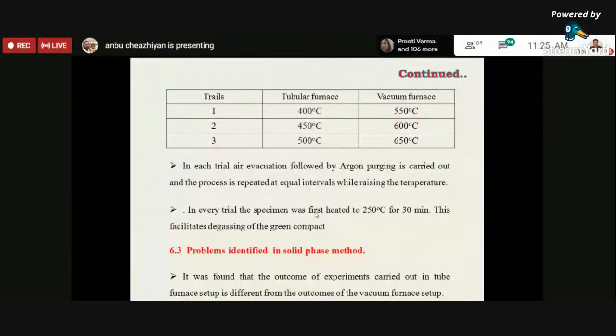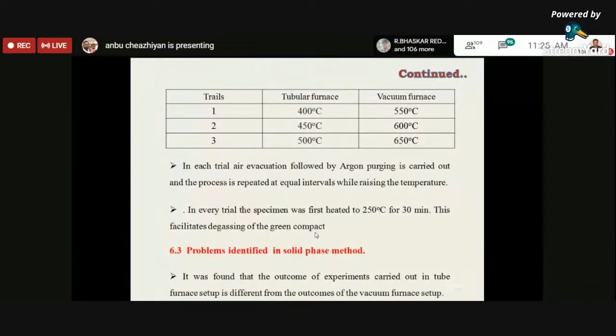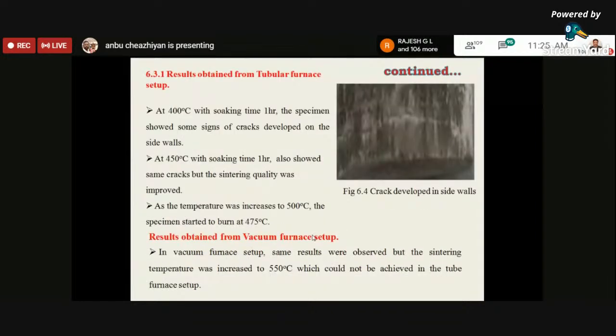Okay, so first, the problems identified in solid phase methods. From the outcome of the experiment, we identified the effect of the sintering process. In a tubular furnace at 400 degrees centigrade with a soaking time of 1 hour, the specimen showed signs of cracks developed on the side walls. Due to the escape of volatile matter or poor wettability, cracks form on the surface of the material. So we decided to increase the temperature to 450 degrees centigrade, but the soaking time was maintained at 1 hour.